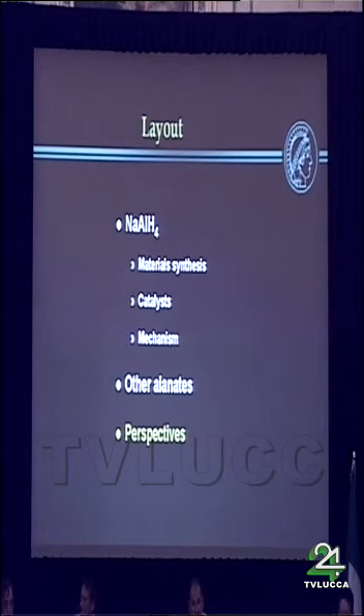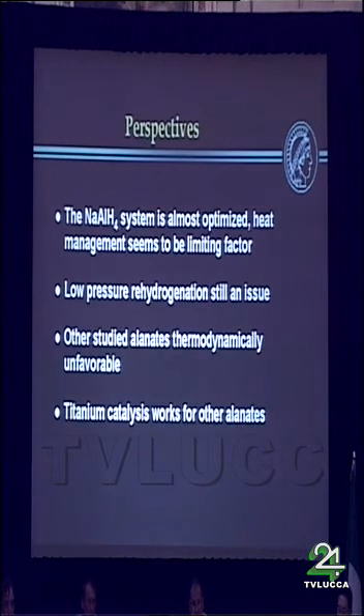With that, I want to summarize with the perspective. I would say that the sodium aluminum hydride system is almost optimized. I'm sure the system can be further optimized to give you the reversible capacity of close to 5% at rates which are below 5 minutes. Cycle stability we have done for some of our materials over not several hundred cycles, but beyond 100 cycles, 130 cycles without loss of capacity.